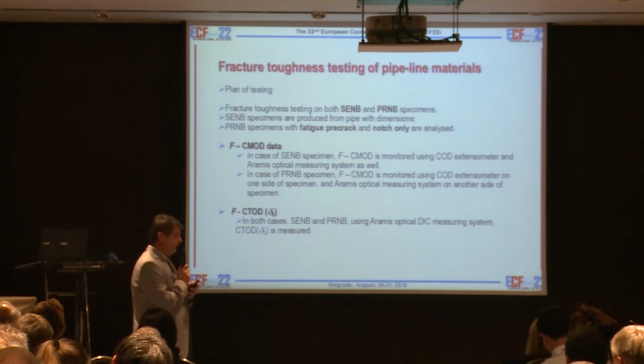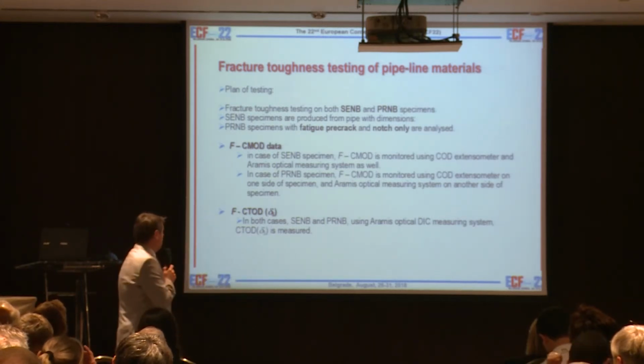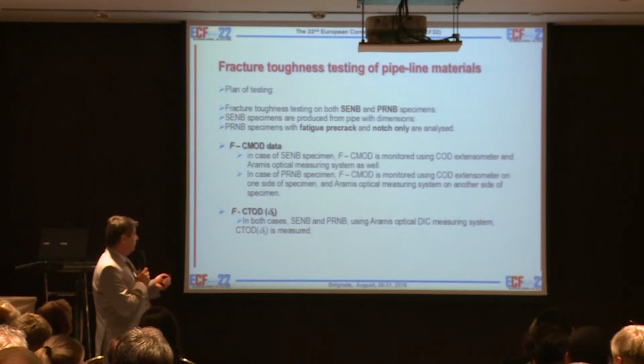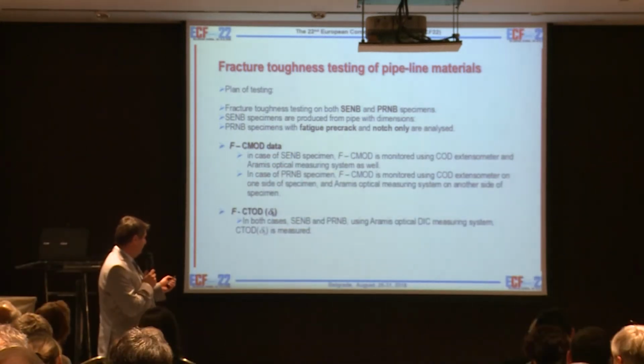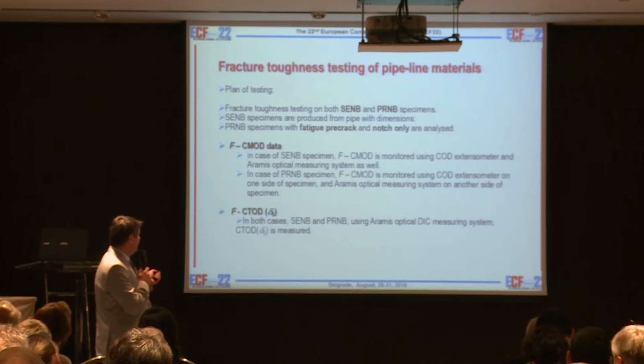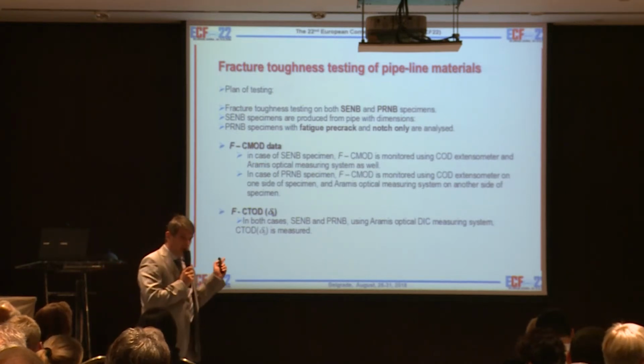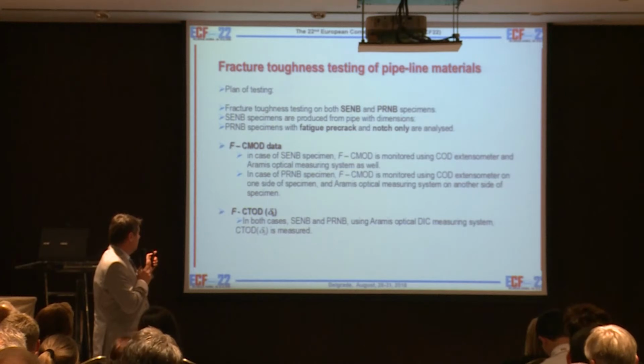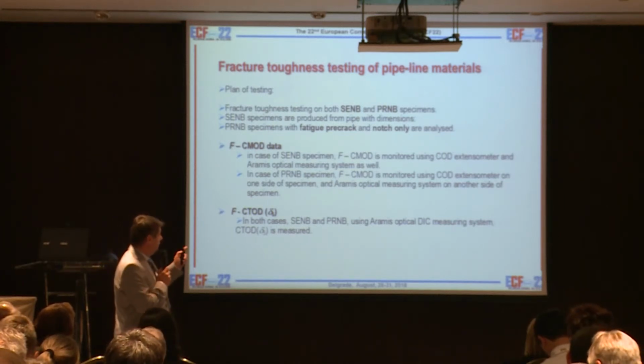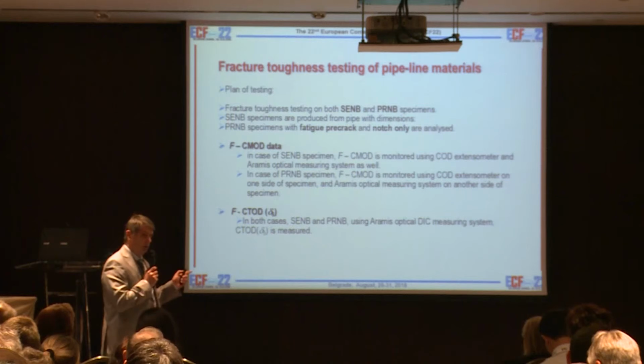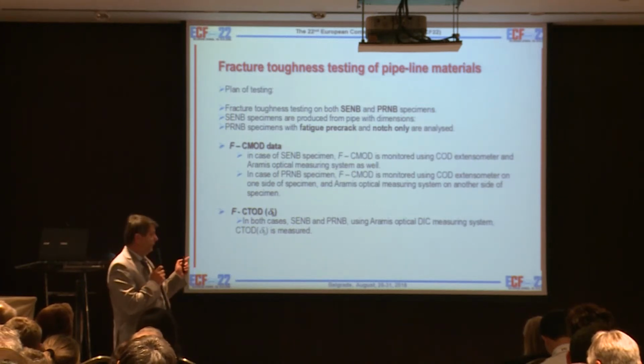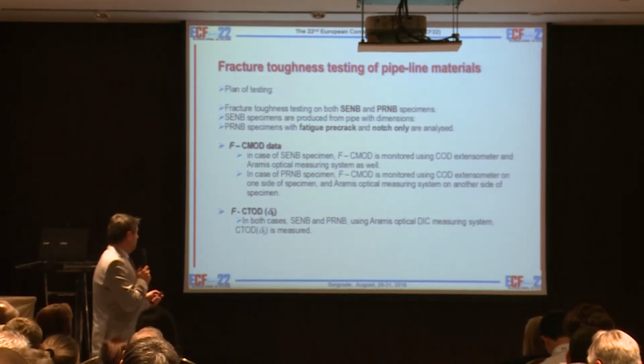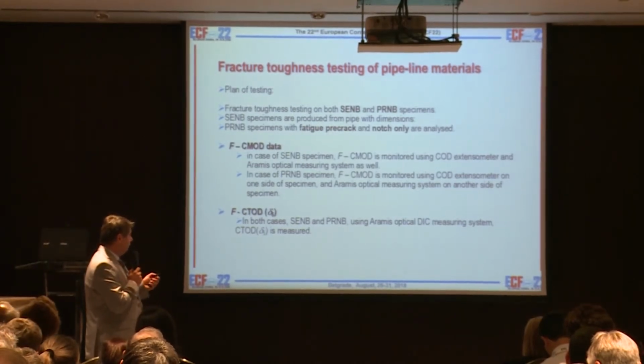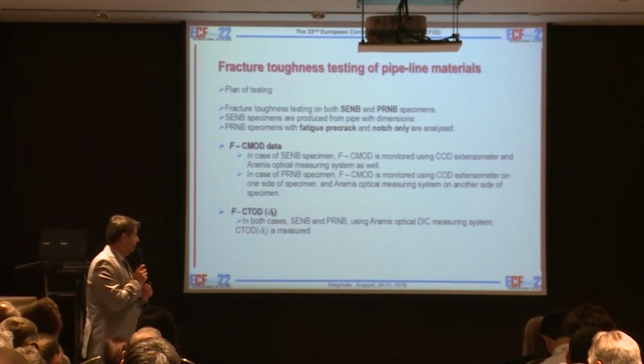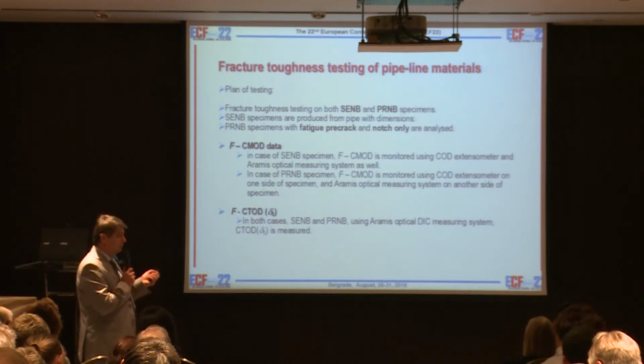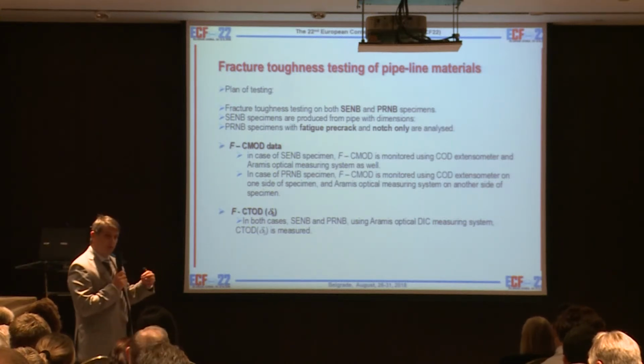The procedure is very similar to the standard procedure. We use the pipe ring specimen and the 3-point bend specimen. For the 3-point bend specimen we made the fatigue pre-crack, and we also did one group of pipe ring specimens with the fatigue pre-crack and one group with notches. During the testing, first, of course, we use the standard procedure for pre-cracking,